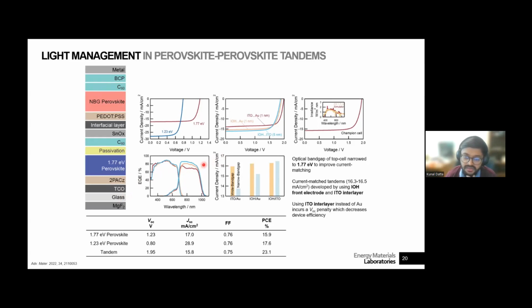But there are some challenges still. So for instance, the first one is the voltage. So the moment, for example, you go from the ITO front electrode to the IOH front electrode, so from this red to this orangish one, you incur a voltage loss. And we're not entirely sure why that is, because energetically, as much as you can measure with UPS, everything seems to be the same. But still you do, and we see that consistently.